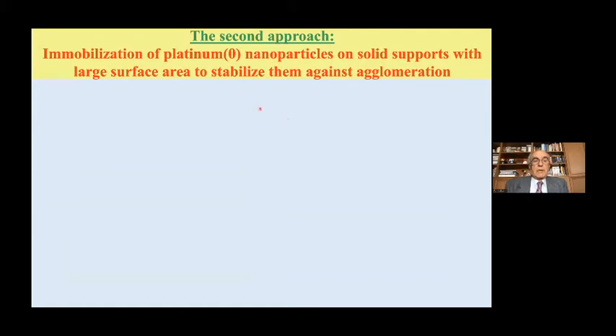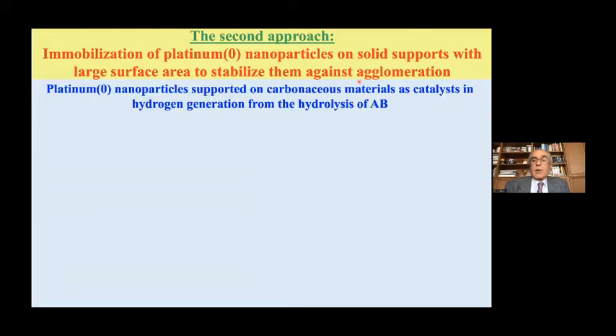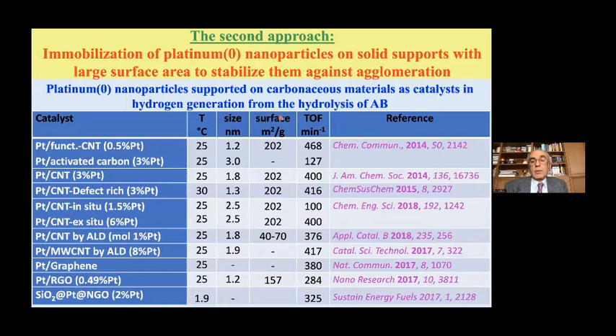The second approach is the immobilization of platinum nanoparticles on a solid support with large surface area to stabilize them against agglomeration. So one of the support materials is carbonaceous ones. Carbonaceous materials can be used as support for the platinum catalyst, many carbonaceous materials like carbon nanotubes or graphene, reduced graphene oxide, and so on. So one interesting point I want to show is that they studied the in situ or ex situ preparation of platinum nanoparticles on the surface of carbon nanotube.